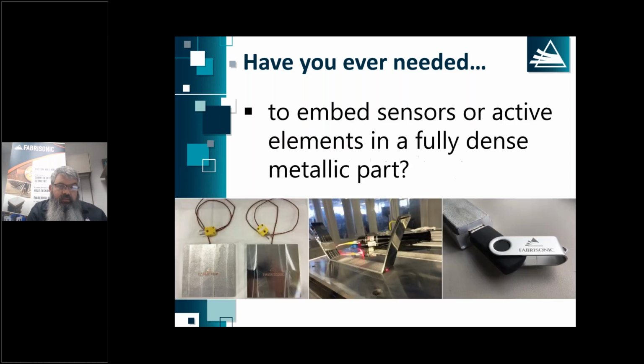There we go. The second thing that we do well is embedding electronics. Ultrasonic additive is different from many traditional 3D printing processes in that we don't take a metal like a powder or a wire and melt that. We're actually taking thin metal foils. The foils are on the range of about 5/1000ths of an inch, and we weld those together at room temperature using a process called ultrasonic welding.